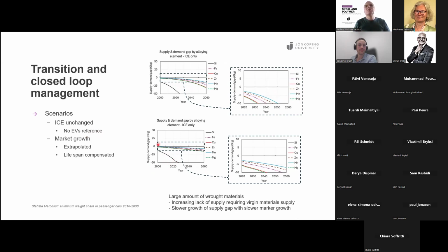You can see that, especially for silicon, there's a small visible knee here, and that is based on the change. So if you then blow up a portion here, you can see that all of them are now lacking. So we will have to add all these elements. There is no time where it goes above this line, where the scrap actually supplies more alloying elements than what we need in our alloys. So there's a constant need for alloys if we continue with the combustion engine.